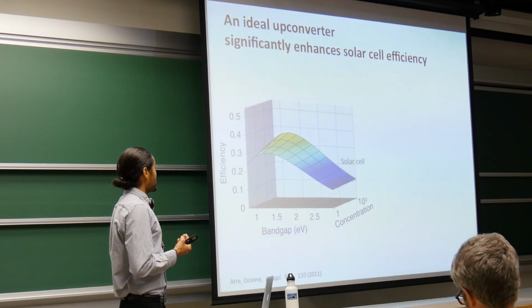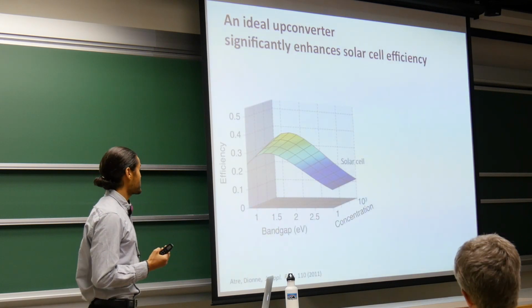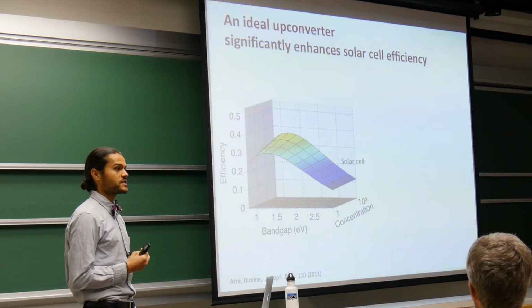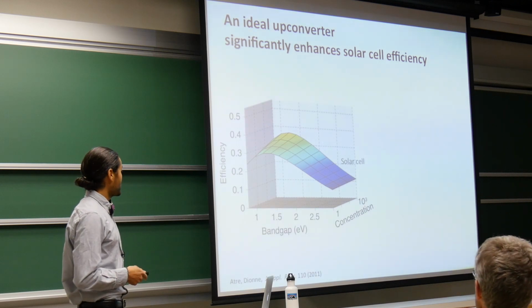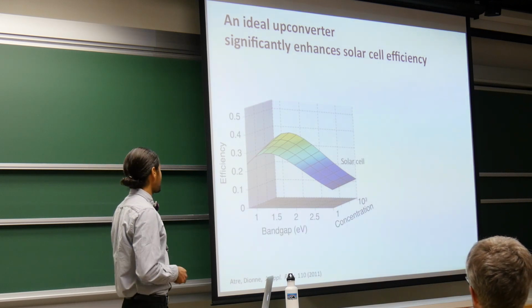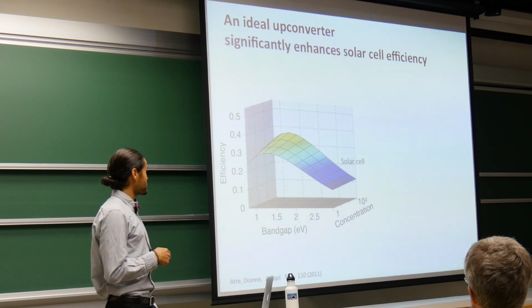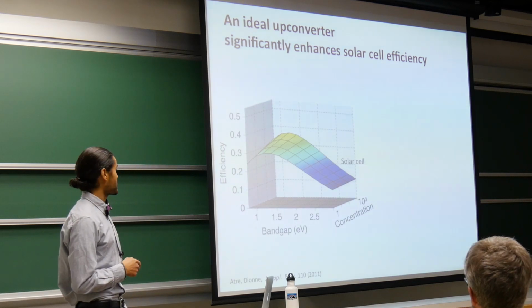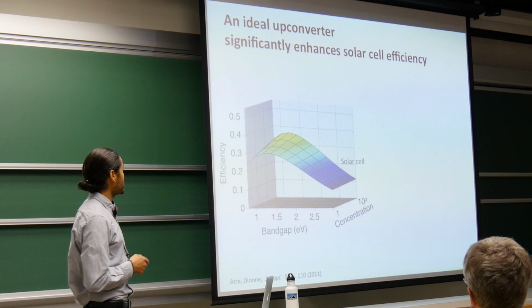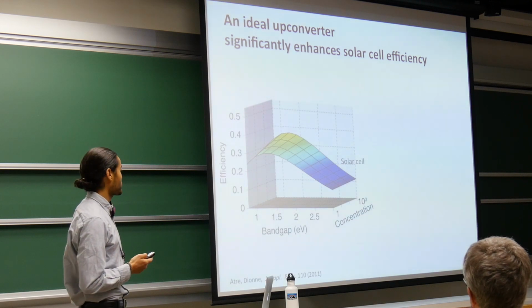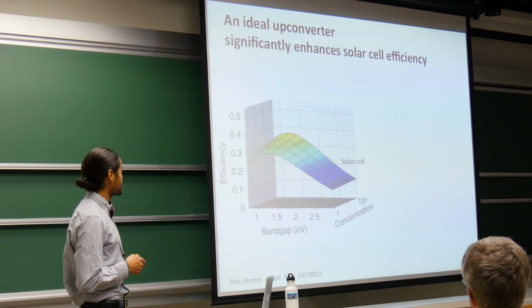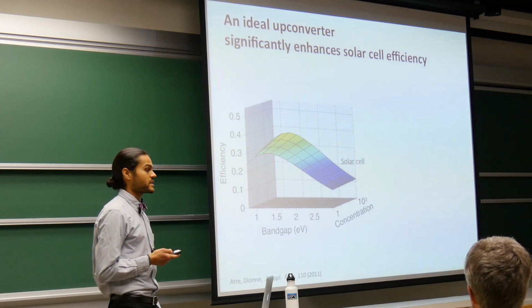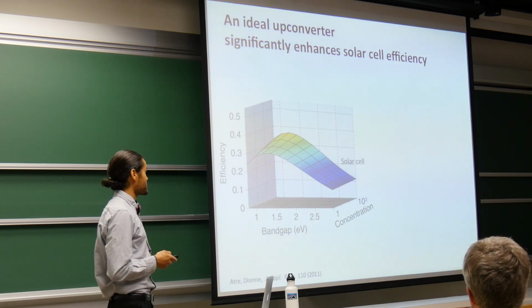So as a basis for comparison, we first start out by just calculating the efficiency of the solar cell on its own. Here I'm plotting the efficiency as a function of both bandgap and concentration, and we can see that for non-concentrated sunlight, we recover basically the curve that Shockley and Queisser calculated about 50 years ago, which peaks at around 30% for a single junction ideal solar cell.